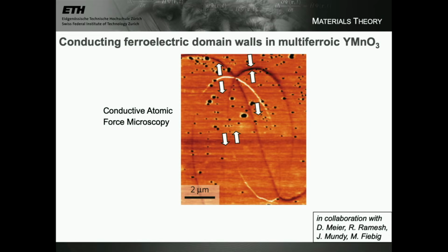And in this picture, this is again a picture of the same domain structure using a technique called conductive atomic force microscopy, which tells us how many carriers, how many electrons or holes, are in the sample spatially. It's a spatial map of the number of carriers. The arrows are the polarization again, measured using piezo force microscopy. And at this region here, where I have the tail-to-tail wall, the bright coloration in the conducting atomic force microscopy is telling me I have an accumulation of carriers.